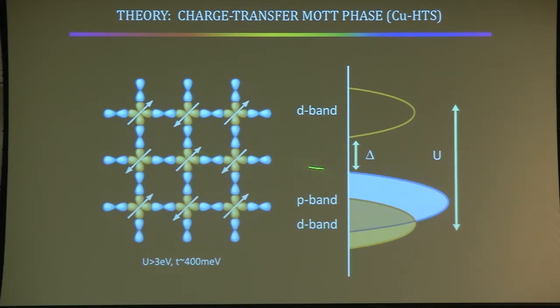And because the oxygen band is in between, the actual magnitude of the gap in the density of states, the charge transfer gap, is about 3 electron volts in the cuprates. This is very well known. The superexchange between these copper spin halves produces the antiferromagnetism. So that's the Mott insulator state of CuO2.